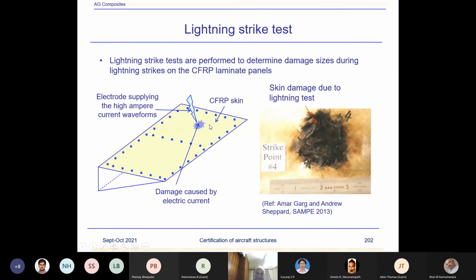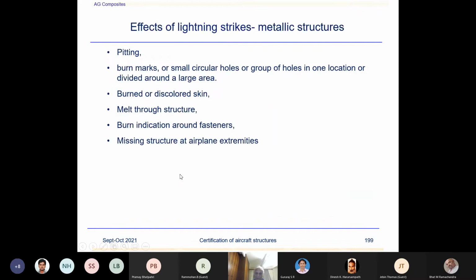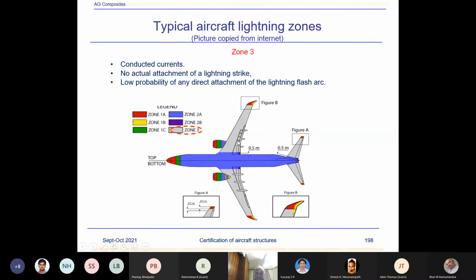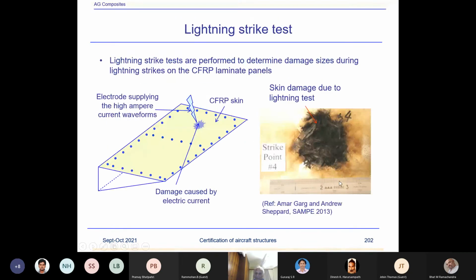And in some regions like these flaps, because these flaps lie in zone 3, which is not a very critical area, no lightning protections were required in the flaps. However, we had to determine, in case something happens, the damage resulting from lightning strike, and also these fasteners. Normally, lightning hits and damages the fastener in service. There have been quite a few cases when lightning has affected these fasteners and created damage in the trailing edges of these flaps in service.